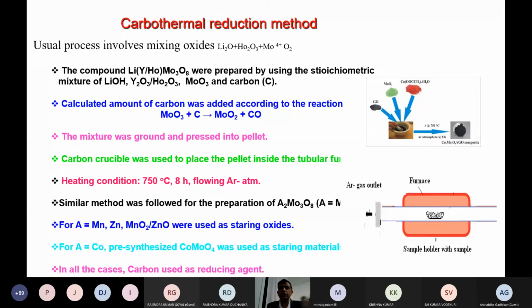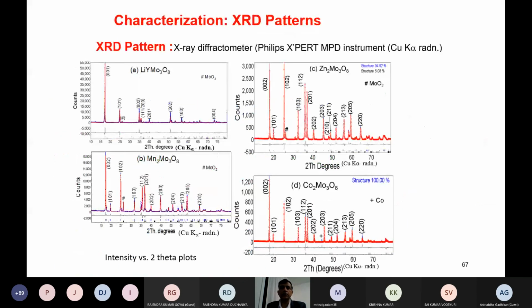You can take any material, and depending on the oxidation state, you can try to prepare the complex oxides. So these are the X-ray patterns. As I told you, we can do refinement. In some cases we can see a small impurity, for example different phases. Remember, if you are working with anodes, a small impurity won't make much difference, especially for cathodes we need pure materials, which is very important for the applications we are targeting.